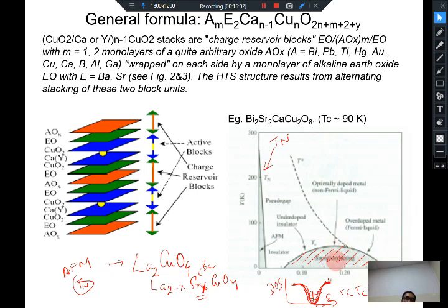However, if you go at a temperature which is above the superconducting transition, people have found that there is still a weak gap which is surviving at T greater than Tc. So if I have the density of states measured as a function of energy, this is your Fermi energy, then for T less than Tc you have a nice well formed gap. This is T less than Tc. But even for T greater than Tc, you will find that there is a weak gap surviving which slowly decreases until it completely disappears at very high temperature.